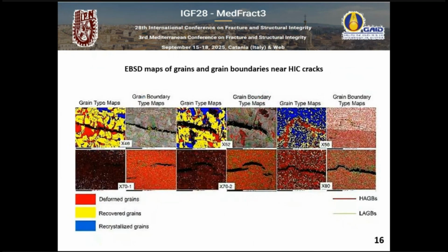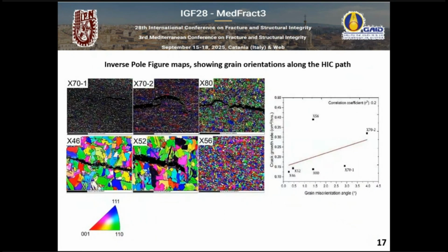We did also some EBSD, and we try to relate the crack growth rate in the individual growth stage with the grain misorientation angle. Again, no correlation, very bad correlation if we take the bulk data. But if we separate the data by microstructure, old generation and new generation, then we see a big difference.